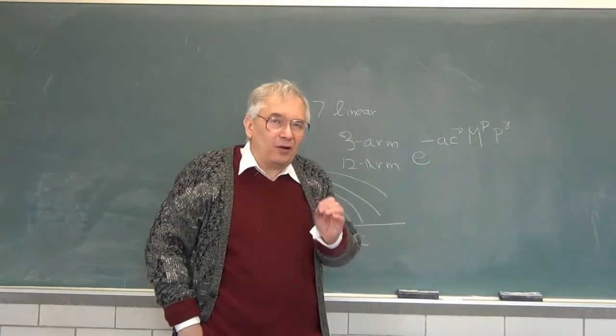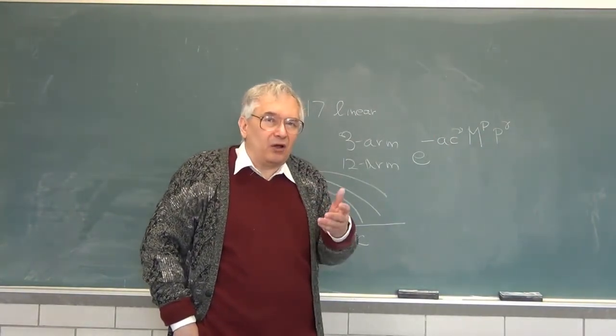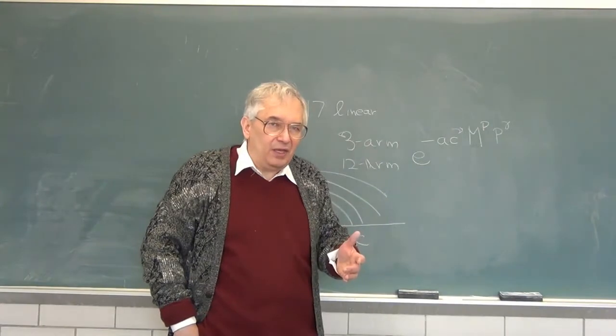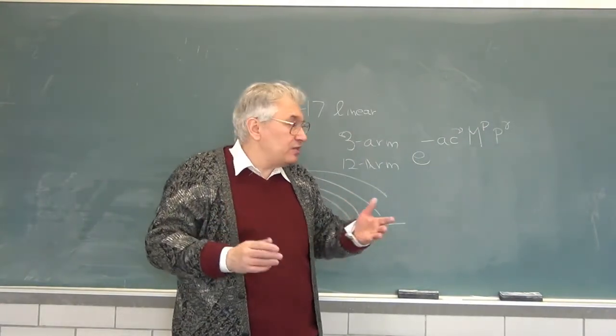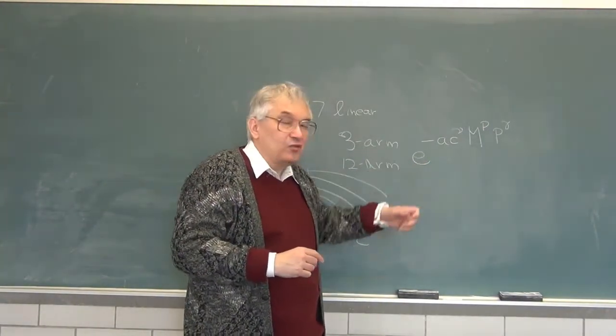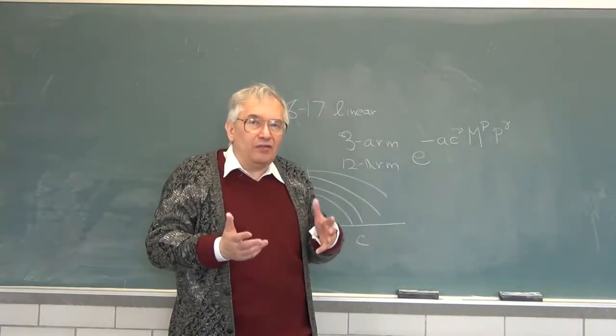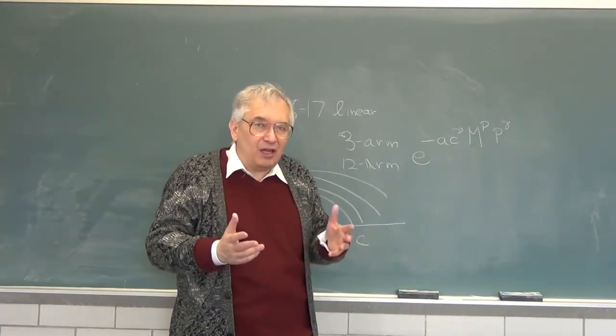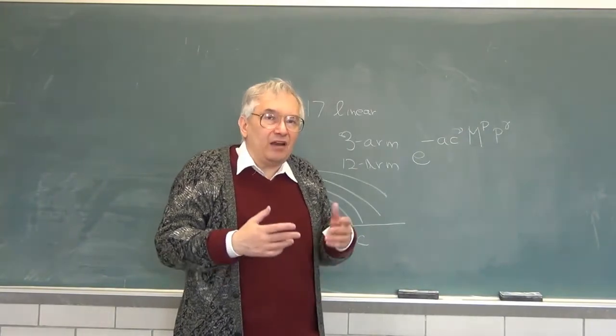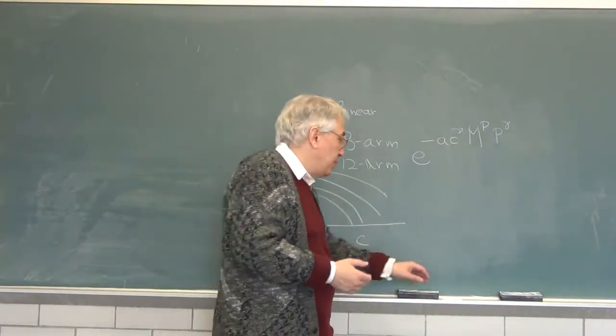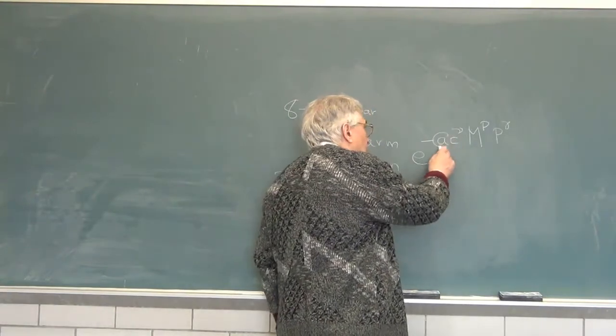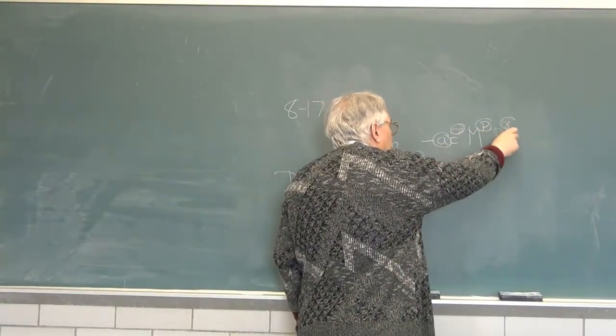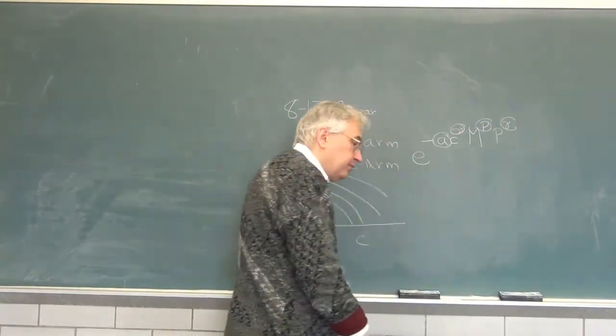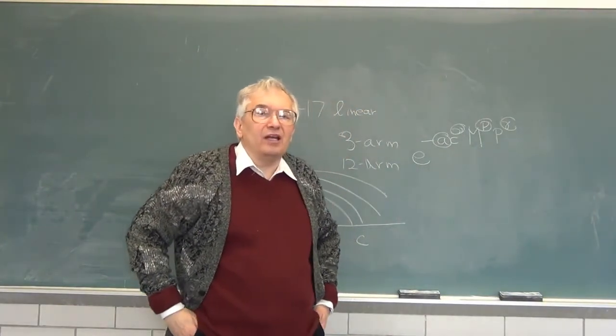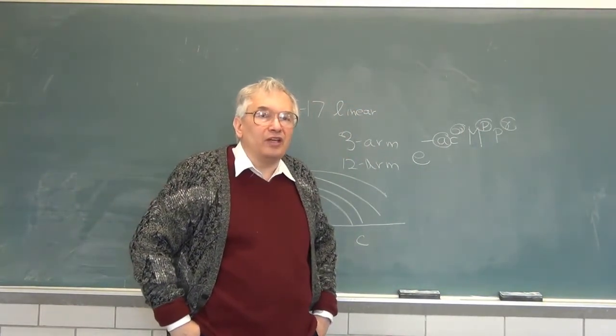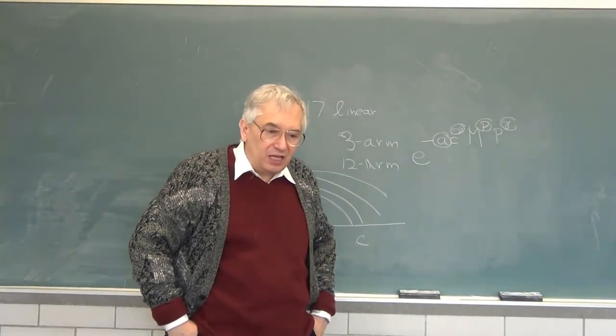And then we do the hard thing, namely we say we will take all of the measurements at the same time, and we will fit all of the measurements at the same time to a stretched exponential. And if we fit all of the measurements at the same time to a stretched exponential, we get a family of 12 curves, all defined by the same 1, 2, 3, 4 parameters. And the curves do a very nice job of representing all of the measurements simultaneously.